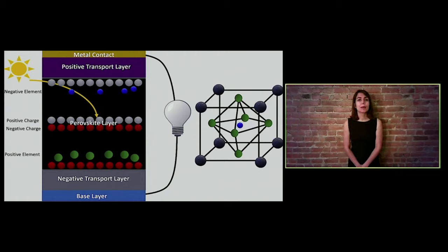This situation is a little bit less severe for positive charges, because after a few rounds of trying, they finally manage to get themselves in the positive transport layer and eventually the outer circuit. However, for negative charges, the struggle is real. They're going to have to try for much longer before they can finally get themselves into the respective transport layer, the base layer, and eventually the outer circuit.